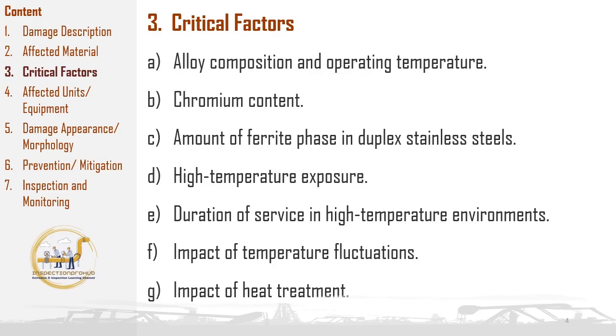To mitigate this risk, duplex stainless steels must be cooled rapidly after welding to prevent the formation of detrimental phases, such as sigma phase or delta ferrite, which can significantly impair the material's toughness and corrosion resistance. Careful control of ferrite content and cooling rates is therefore essential to maintaining the integrity of duplex stainless steels in high-temperature environments. Fourth critical factor is high-temperature exposure.